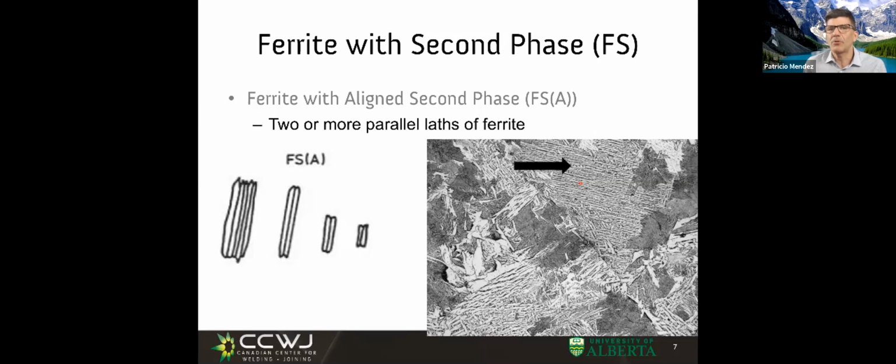It's less tough, of course, and you can see the crack patterns that can develop here, right? Well, acicular ferrite is a basket weave, and it's very tough because whatever you do is kind of all interwoven. This one is like a zipper that can unzip, right? So we see two bainitic types of microstructures, one that has lots of toughness, one that doesn't.